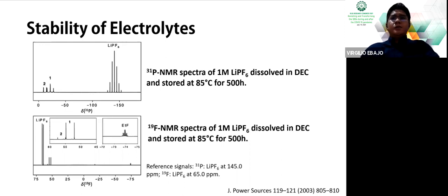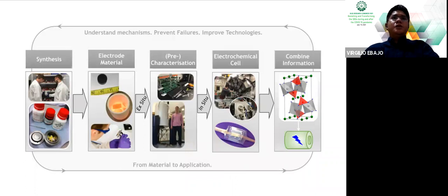And these are signals coming from degradation products, and they are not due to the lithium hexafluorophosphate present in the electrolyte. Now, degradation of electrolyte may lead to undesired events such as short circuit, which in the presence of the usually flammable electrolyte could cause thermal runaway, for example, fire and explosion. Of course, everyone's aware of the Samsung Note 7 battery explosion. And the battery in Samsung Note 7 is a lithium-ion battery. So in order to prevent failures and improve lithium-ion batteries, it is strongly recommended to include NMR analysis in the research and development process or R&D stage of LIB generation.